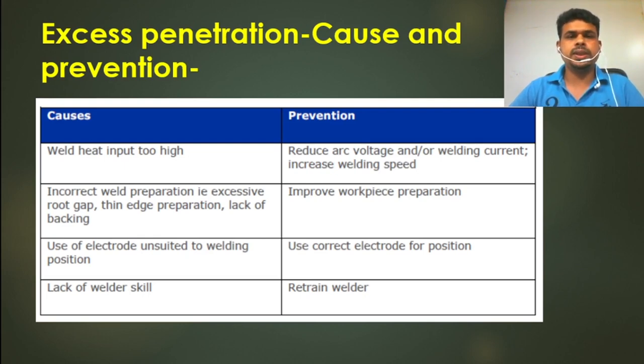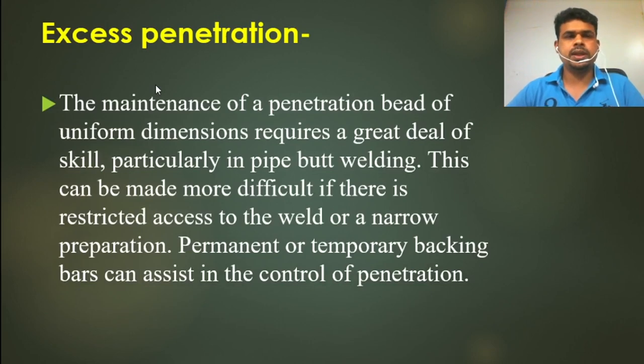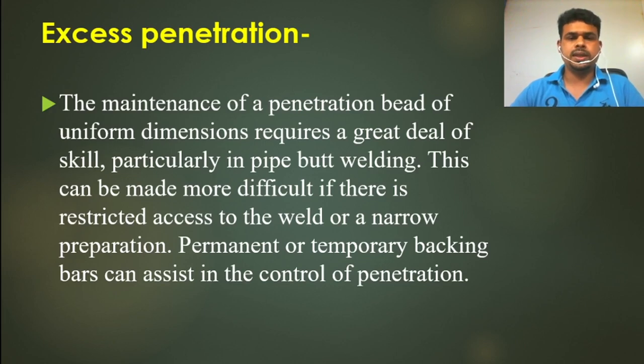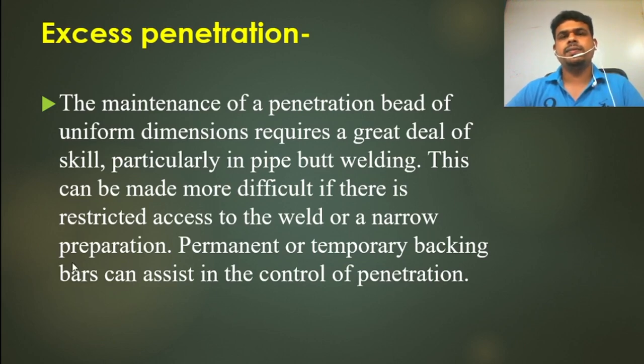We need to train our welders to strictly follow the WPS. If we follow the WPS strictly, we should not get this type of problem. Note: maintaining correct penetration bead dimensions requires a great deal of skill, particularly in pipe butt welding. This becomes more difficult if there is restricted access to the weld or narrow joint preparation. Permanent or temporary backing bars can assist in controlling penetration. For pipe welding where we cannot access the root side, we need proper joint preparation and qualified welders.